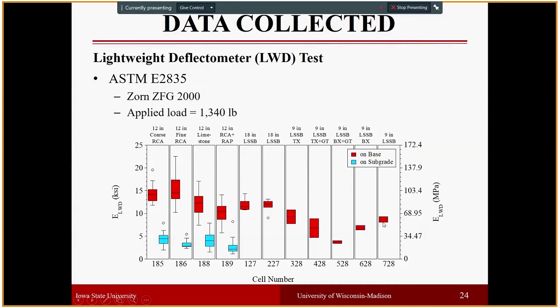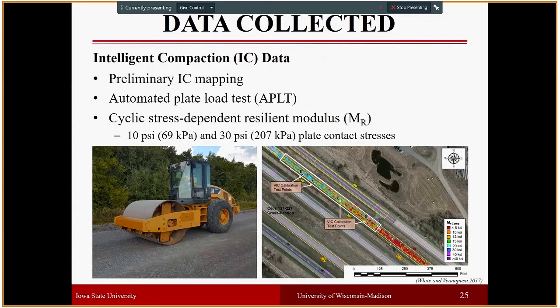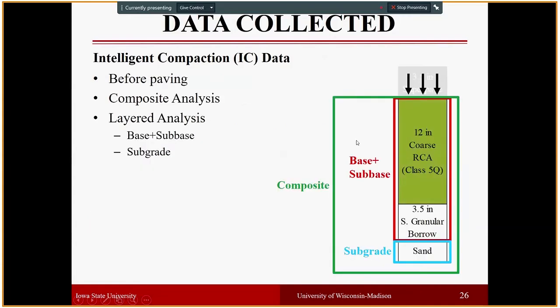And then the intelligent compaction data was collected by Ingios and the University of Texas at El Paso and shared with us. Basically, after the preliminary IC mapping occurred, on top of the cyclic stress-dependent resilient modulus, an automated plate load test was conducted on the test sections at different plate contact stresses. And the analyses were done in two ways: one is a composite and one is a layered analysis.